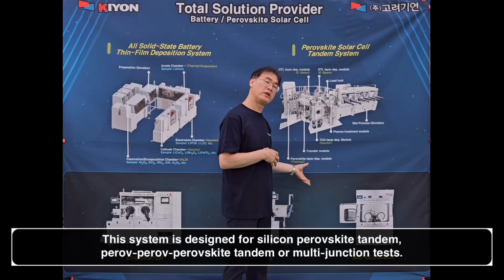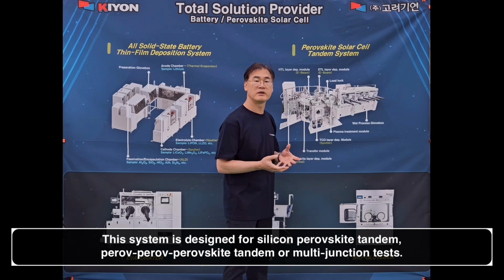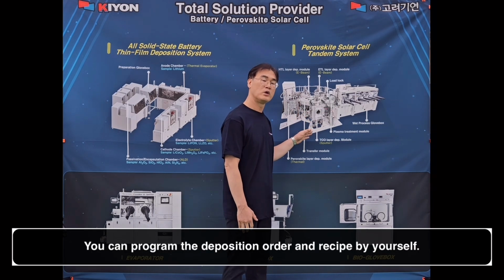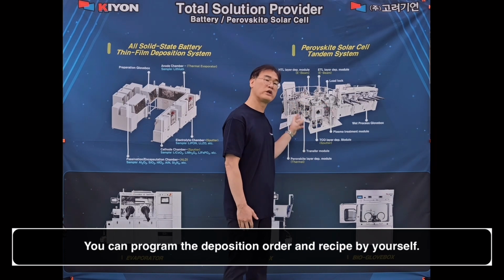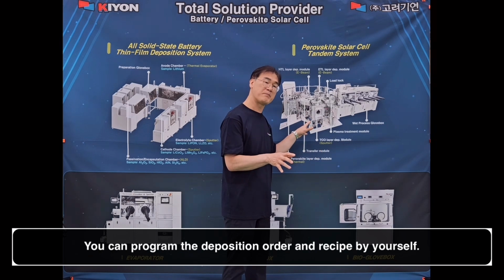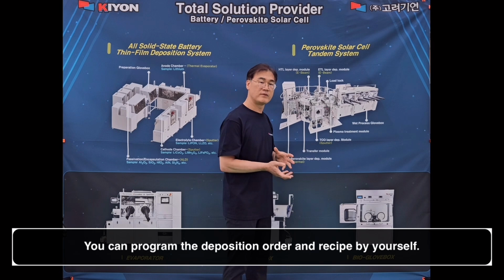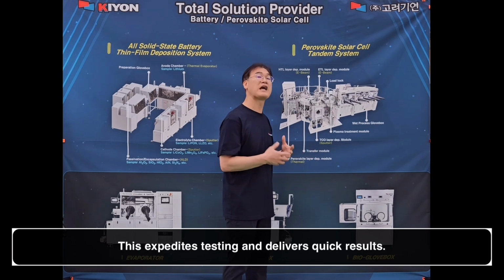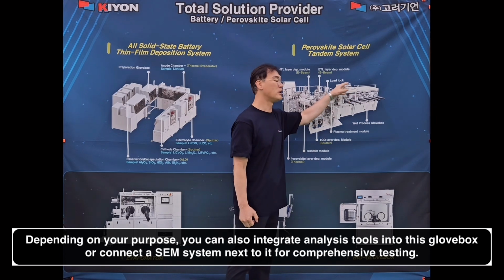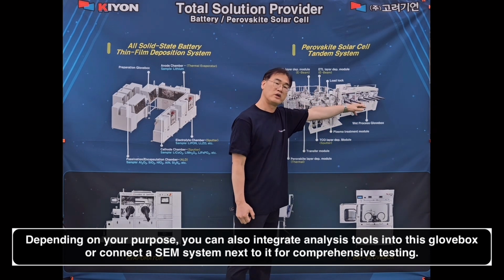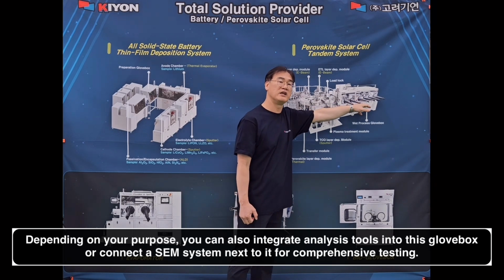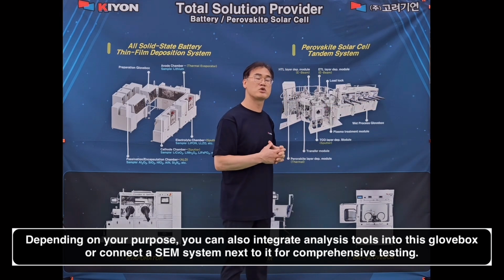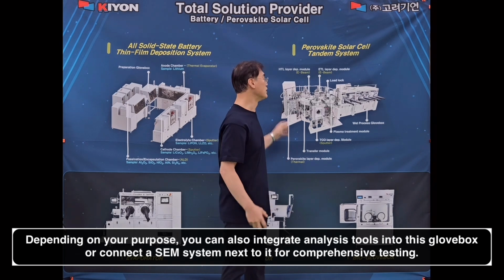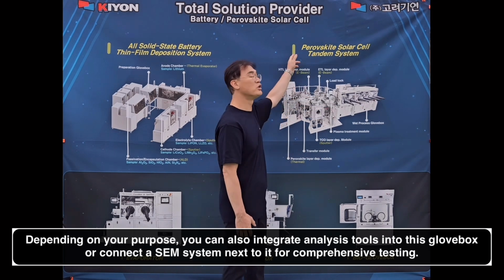This one is actually designed for silicon-perovskite tandem, perovskite tandem, or multi-junction kinds of tests. Depending upon your material or what you want, you can program the chamber deposition order recipe by yourself, so that this system can expedite your testing and get the results very quickly. Also, depending upon your purpose, you can put your analysis tool in this Glovebox, or by connecting a SEM system right next to the Glovebox, you can have a total testing through this combined complete system. This is the beauty of our system.